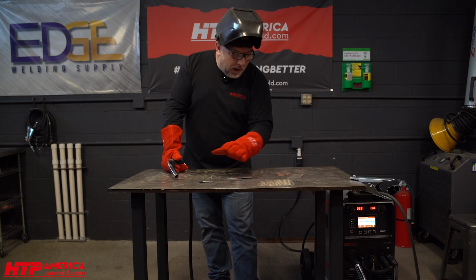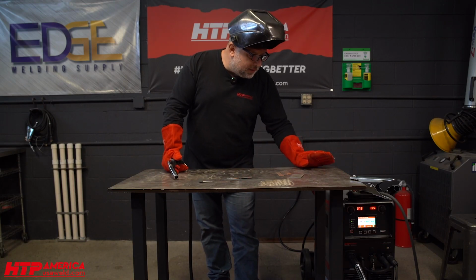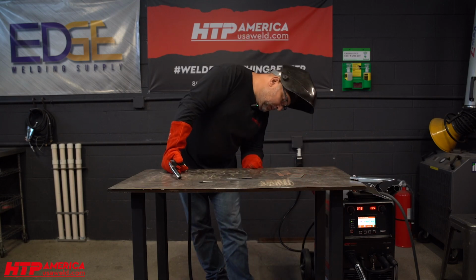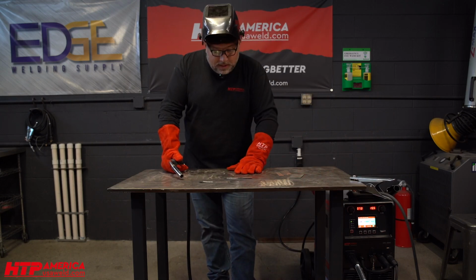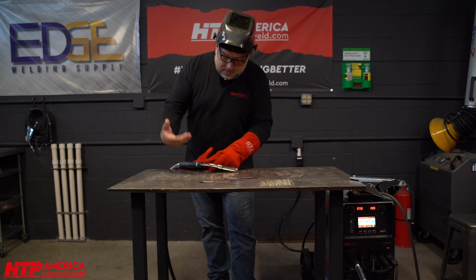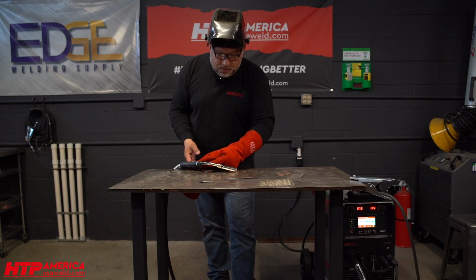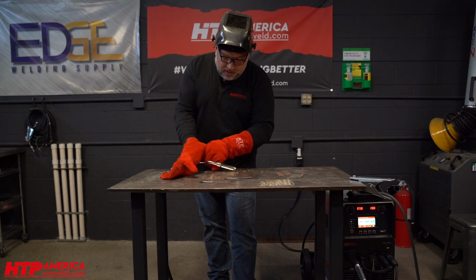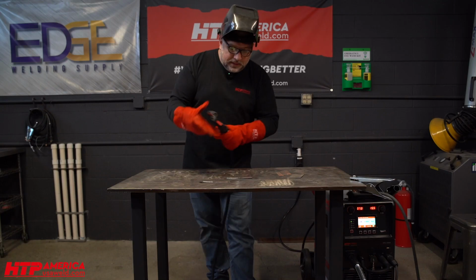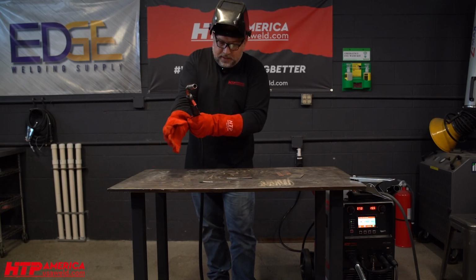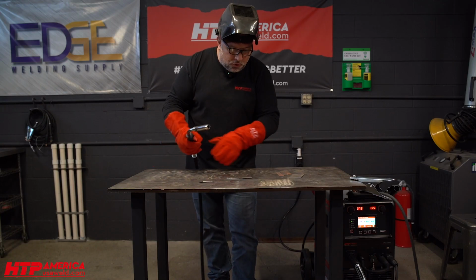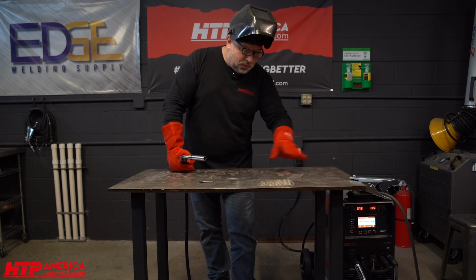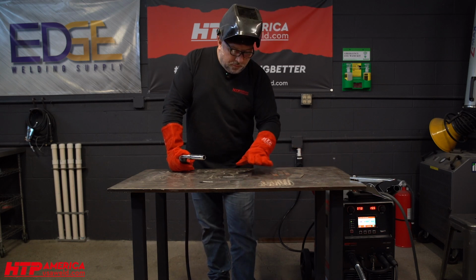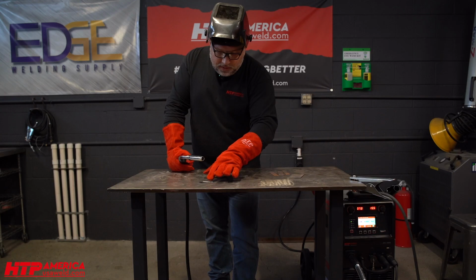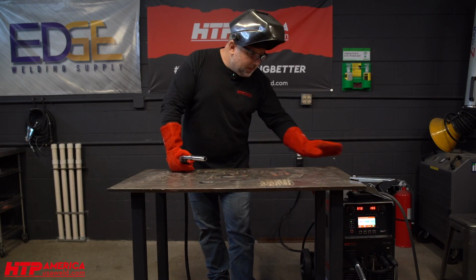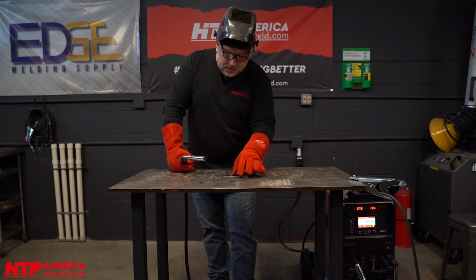Now, why do we have this? Why weren't the machine settings correct right out the box? Well, this is a 5/8 plate that's laying on here, and it's ice cold, 60 degrees at best. So if you have your piece of metal laying on that heat sink, it sucks the heat right out of the weld joint. In order for those settings to be correct, I should have probably propped this up in the air and then the first setting would have been right, but that's where there's a little bit of operator variance.